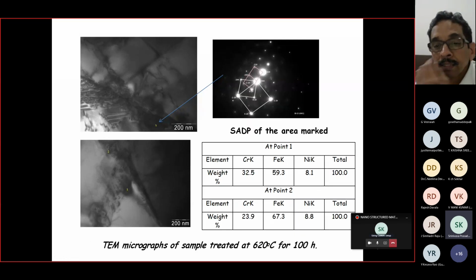Now, this is the transmission electron micrograph, TEM micrographs, of the sample treated for 100 hours. This is an area somewhere near the grain boundary. We tried to identify this particular area, which we felt was a chromium depleted region. Let me tell you one more thing. In this particular image, this dark region and white region, the dark region must be a place where there is a high atomic weight or atomic number. That is the reason why it is so dark.